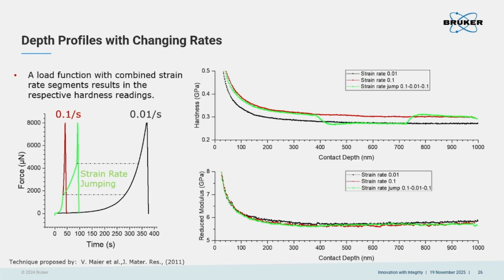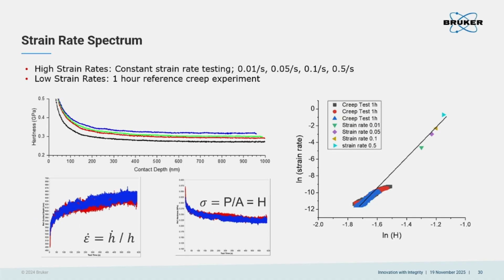This is the only example I would like to share with you for a polymer indentation test. We can have another viewpoint of rate sensitivity and go into a deeper observation. We are able to take a look at a total of 4 different strain rates, so we have 4 totally different hardness responses shown here. And on the other hand, we can also do creep testing to get the strain rate changing with time during the force holding segment. Then we have this region of hardness changing with the strain rate.